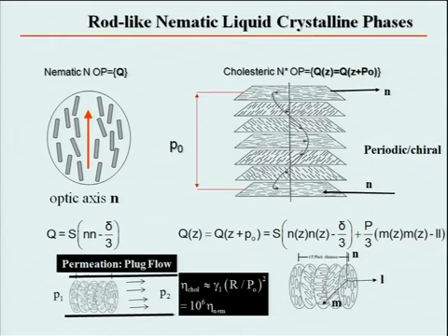And this is a fast variable, a nanoscale variable. Here we have the optic axis, which is the slow variable in the system. It usually describes topological defects and lives in the micron range. Many biological systems, which is the topic of this presentation, display the cholesteric phase.